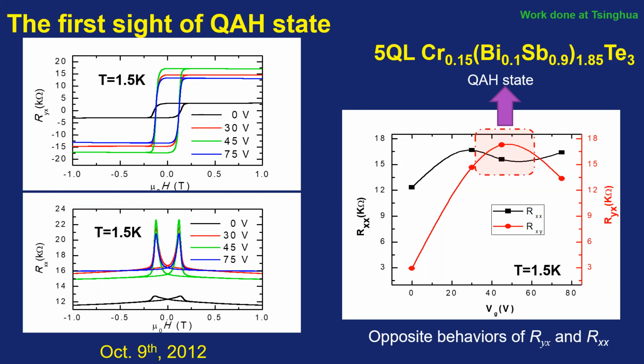In this sample, the Hall resistance is almost 17 kilo ohm, and the longitudinal resistance is also almost 16 to 17 kilo ohm. The Hall angle is almost 1. The reason we decide there is a quantum anomalous Hall state in this sample is because of this.